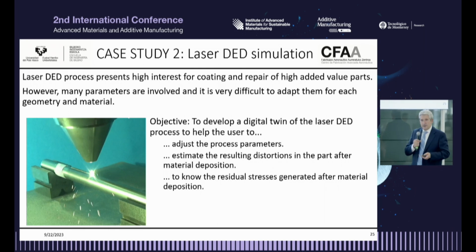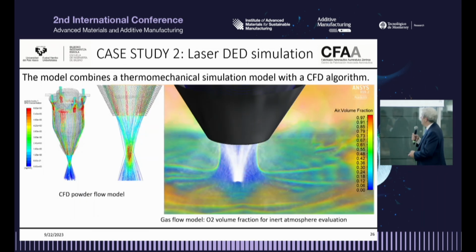And there are a lot of parameters. So the idea is to develop a digital twin in order to set the parameters and also estimate the temperature and the residual stresses, and we are ongoing with that. Here you have some examples. This is the model for the powder and the gas flow. Then we have here the powder concentration. We can even analyze the oxygen concentration or the volume fraction for the inert atmosphere in order to ensure that we are not oxidating the material.